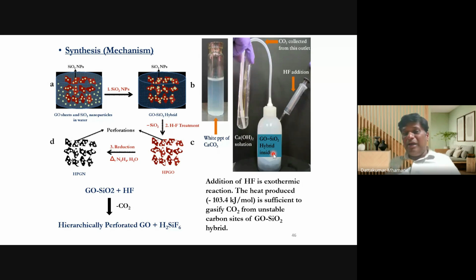So why the hole is forming, the explanation is here. When we add HF, silica is removed with carbon as carbon dioxide. So this is a standard test we have done here. When a calcium hydroxide solution reacts with carbon dioxide, it produces a white precipitate. So we concluded here that the carbon attached to silica is removed in the form of carbon dioxide. We proved here that whatever carbon is present in this graphene oxide-silica hybrid, after HF treatment there is an evolution of carbon dioxide gas, you can see, and this carbon is coming from this graphite oxide. It means that it is creating a hole inside the carbon matrix, 2D carbon matrix or graphene matrix, we can say. So we have proved that, and our paper got accepted there.